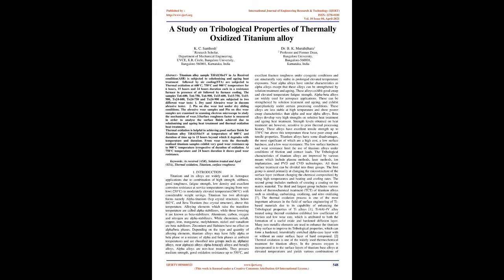for 6 hours, 15 hours and 24 hours duration each in a resistance furnace in presence of air followed by furnace cooling. The samples TO6-600, TO6-750, TO6-900, TO15-600, TO15-750, TO15-900, TO24-600, TO24-750, and TO24-900 are subjected to 2 different wear tests: 1. dry sand abrasive wear in a Ducom abrasive tester; 2. pin-on-disc wear test under dry sliding conditions.